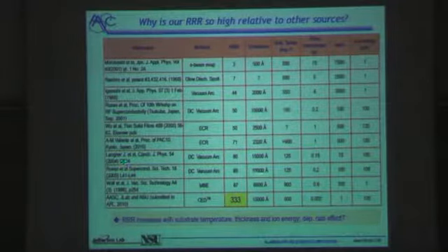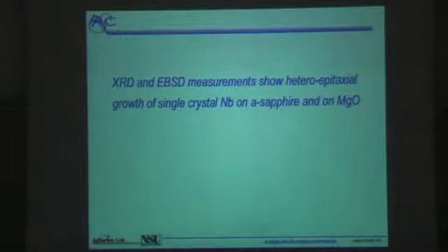It comes back to what I said. We grow a monolayer in about a millisecond. If I normalize to that rate, which is an instantaneous rate of about 5,000 angstroms, 500 nanometers per second, is the instantaneous rate at which this device is laying down material on a film. If you look at all the other experiments, they were 2 to 3 orders of magnitude slower in terms of achieving the same film thickness. Is that significant? I don't know. We need to study that some more.